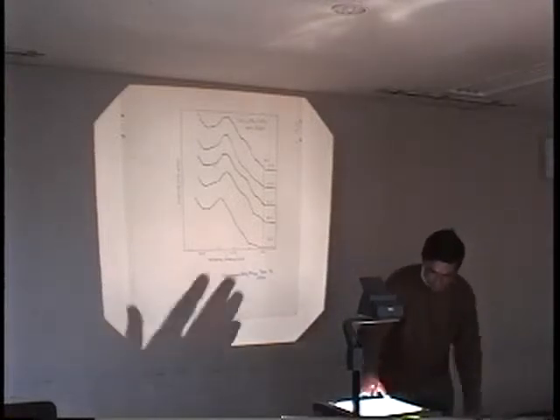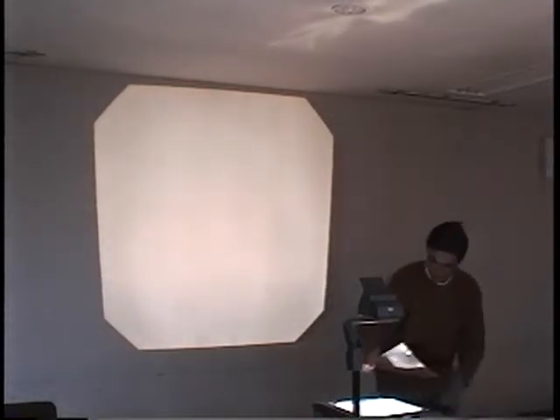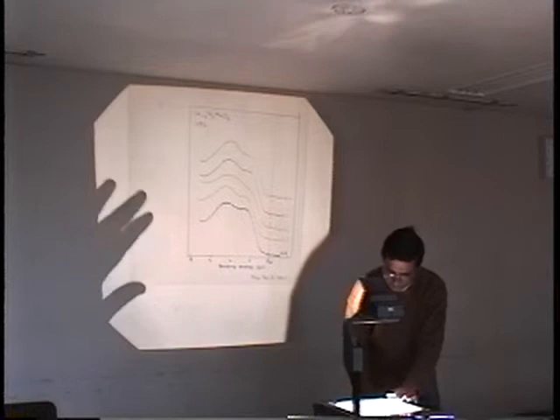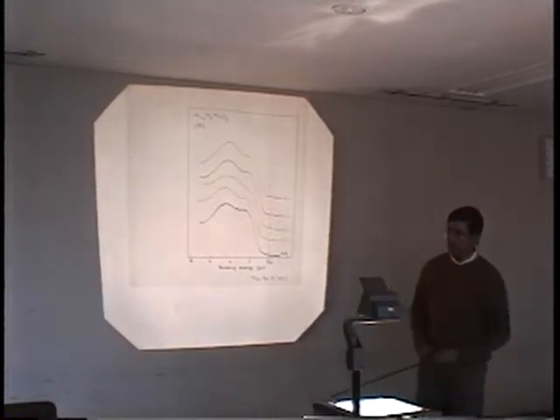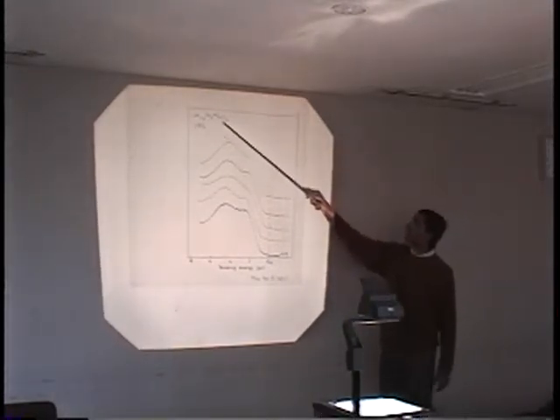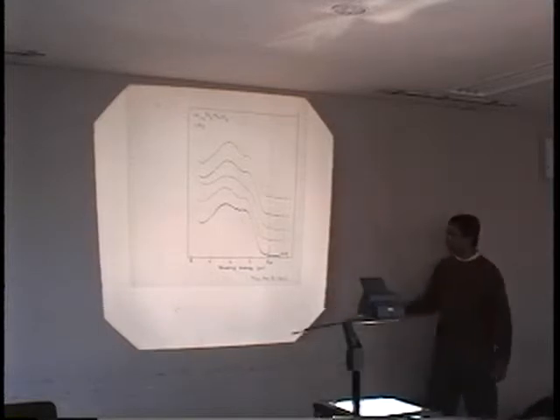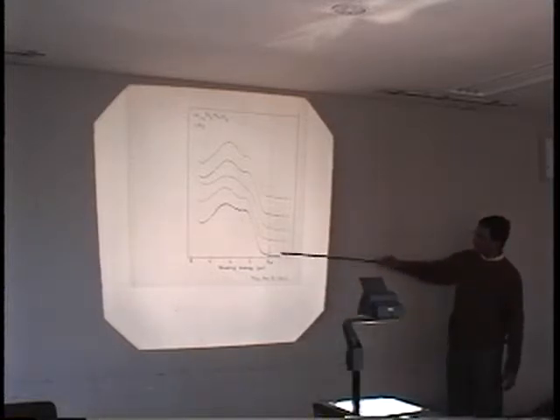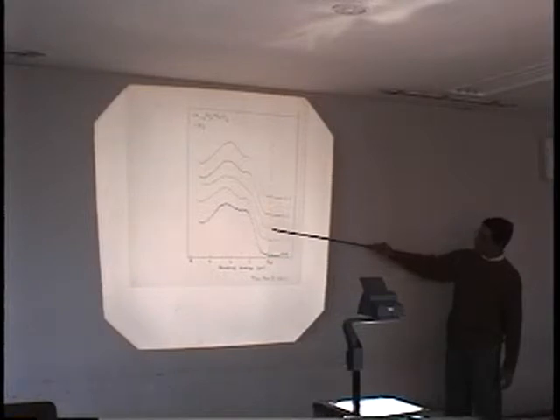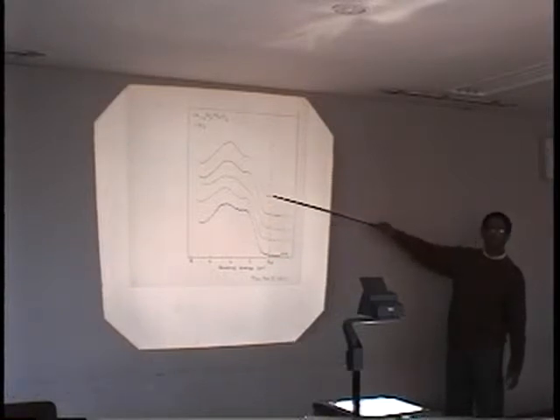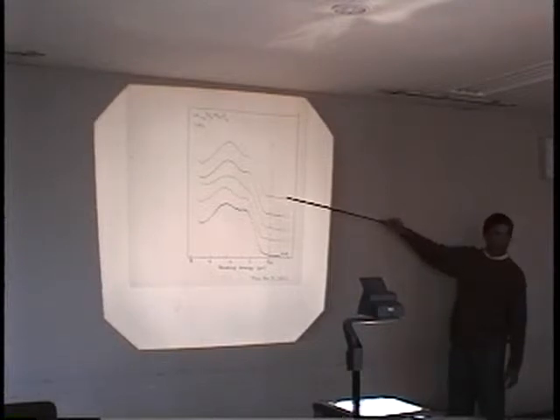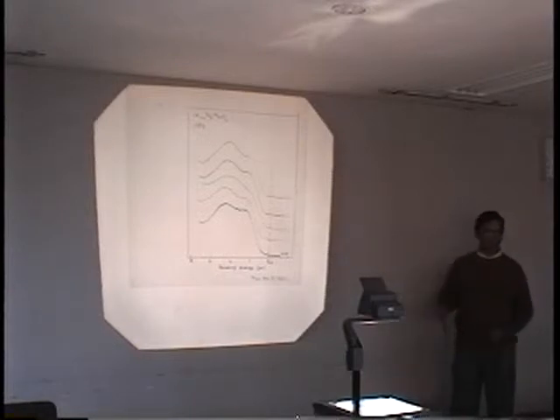Compare this with the behavior of lanthanum strontium manganese oxide. There's another paper that was published in 1993. Now lanthanum manganate doped with strontium. This is lanthanum manganate Fermi energy. There's no density of states at the Fermi energy, and as we go, one doesn't see any density of states at Fermi energy, even for such doping, which shows an insulator to metal transition. So this looks very unusual.